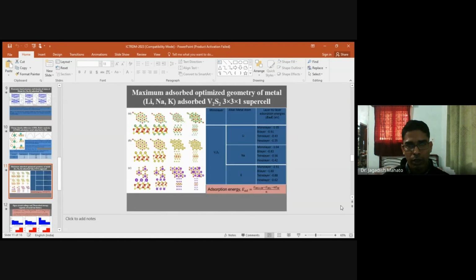Then to calculate the capacity and OCV, we adsorb as many atoms as possible. At first we covered with the monolayer, then we covered with the bilayer, then tetralayer and hexalayer, and calculated the adsorption energies, which are tabulated here. On the left hand side you can see the first row shows the top view and side view of the lithiated V2S2 sheet, that is the geometry optimized structure, and B shows the sodium adsorbed V2S2 structure for monolayer, bilayer, tetralayer and hexalayer, and the same goes for potassium in figure C.